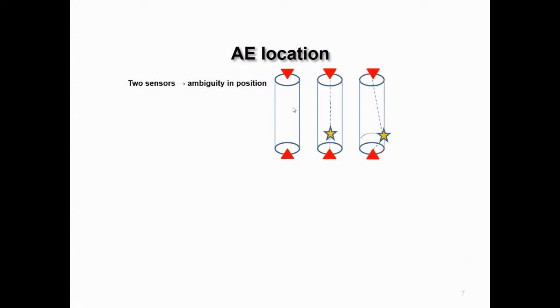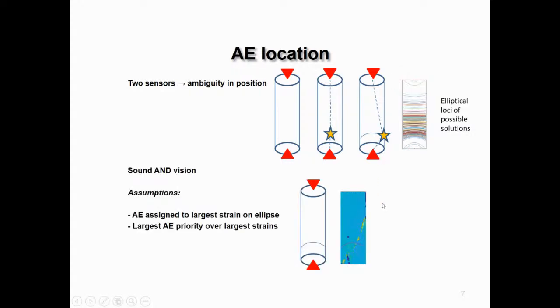So we're limited to 2 sensors. So all we can do really is map out a whole load of possible positions as a kind of bowl here from the 2 travel times measured above and below the sample. But we also have the information from the strain, so we can pick the most likely location as the intersection of this bowl with the area of high strain.